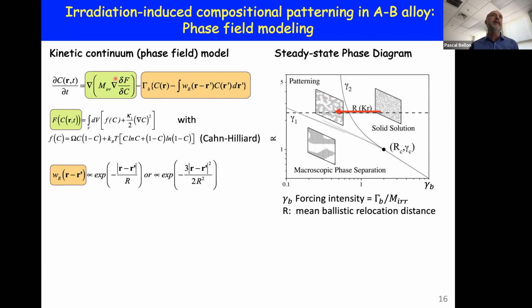So in green, for instance, this is the thermally activated diffusion that's responsible for phase separation in this alloy system. For that, we're going to use a traditional Cahn-Hilliard free energy for an inhomogeneous system. Some of you might be familiar that in that case, we have a free energy density for the homogeneous state that is essentially a regular solution model with an interaction parameter omega and this entropic contribution. And then there is an energy penalty due to the formation of interfaces, with this gradient energy coefficient kappa 1. And so now this is for the first dynamics.